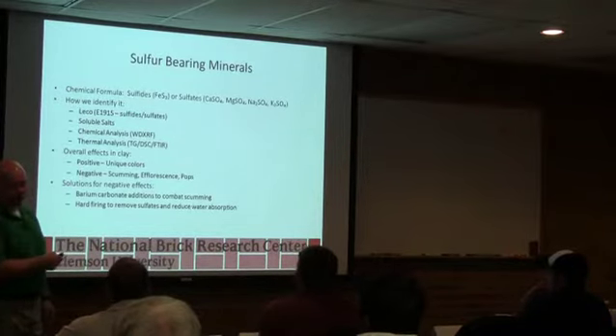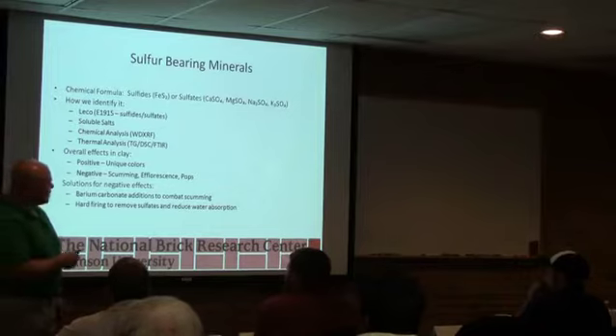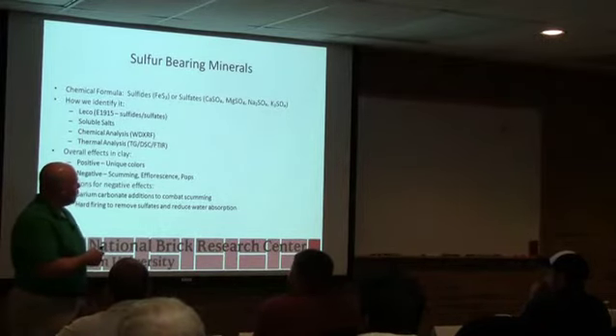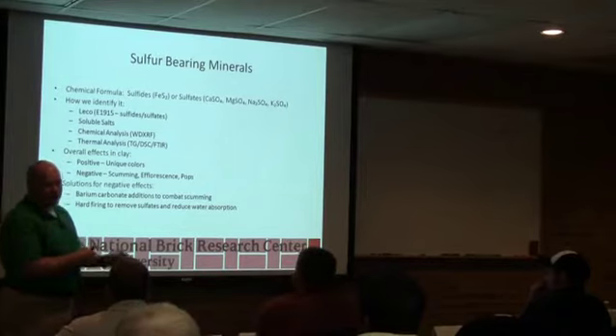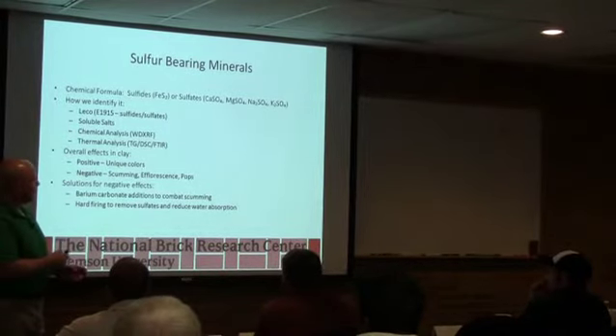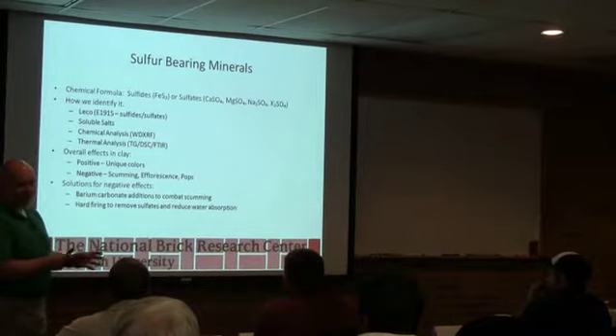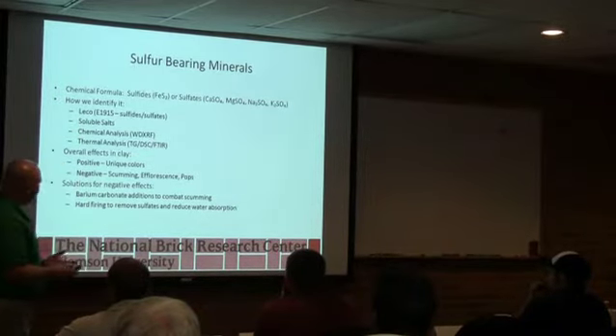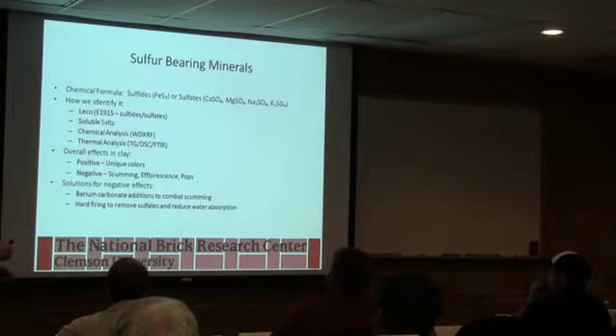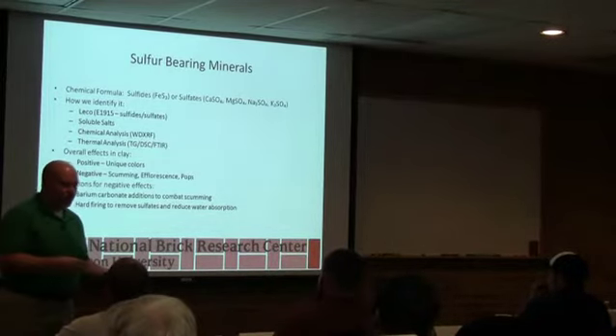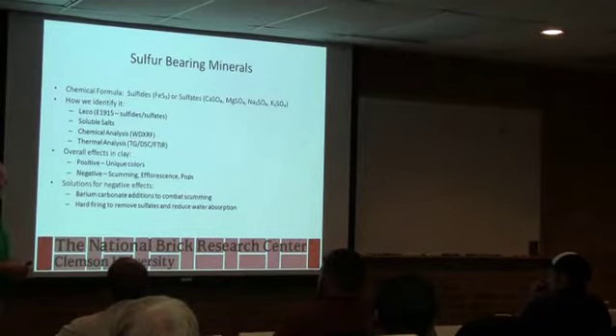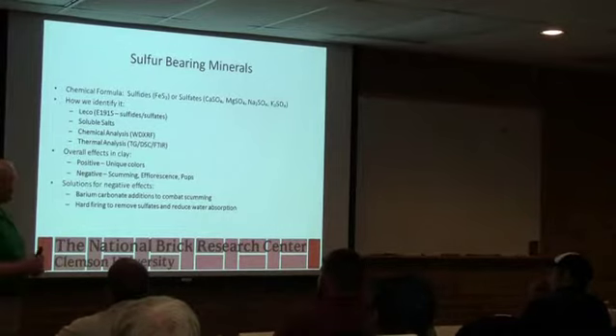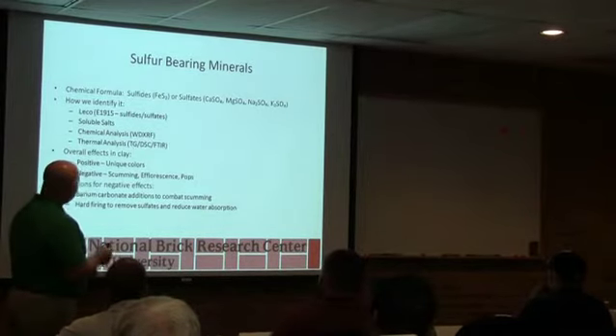Efflorescence happens after it gets out, and sometimes you see it in the cube, sometimes you see it in the wall. These salts can actually also come from the mortar. Mortar has a lot of gypsum in it to give it early set strength, so not all efflorescence is due to the brick. Because of that, we've done a lot of work trying to come up with a test, and we have a soluble salt test where there's usually a tracer, and we can figure out whether the efflorescence came from the brick or from the mortar. And 9 times out of 10, or let's say 9.9 times out of 10, it's coming from the mortar if it's from a job, and we can pretty definitively show that.